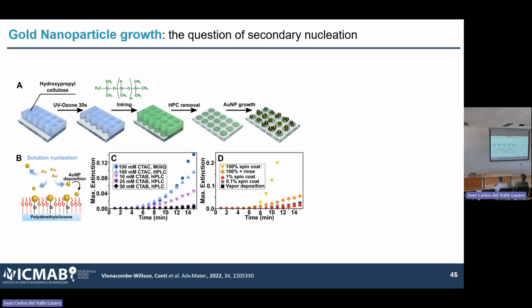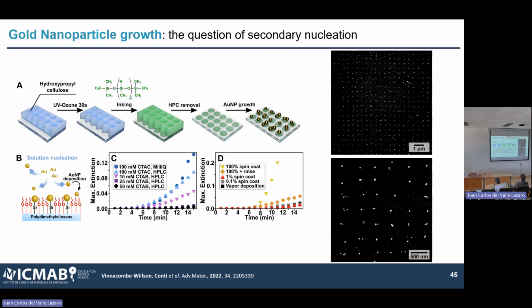These, of course, didn't work at all because, as I said, we need to control the secondary nucleation. The way we control the secondary nucleation is we play around with the composition of the surface. I'm not going to go into the detail here, but basically we try to identify conditions where, at least for 10 minutes, we were not able to see any nucleation in solution. These are basically UV-visible measurements done on the solution. And then we chose those conditions and we stopped the growth at 5 minutes. So that was our idea. And by magic, it turned out that we could finally observe some patterning.